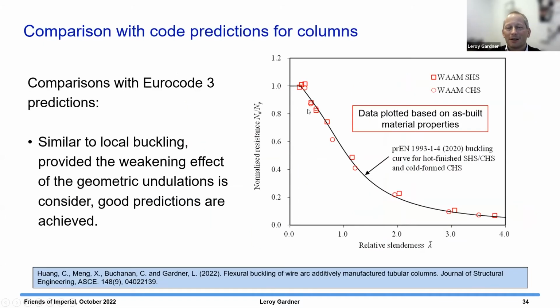And if we plot the data, so we're now talking about member buckling. This is called a relative slenderness here, which is about the length of the column. Longer columns are moving to the right, and same as before on the vertical axis. Actually, the data points, these ones are plotted based on the as-built material again, and they're following pretty closely the existing buckling curves. So again, this gives confidence in the fact that whilst this is a new method of production, things are still behaving roughly as they should do.